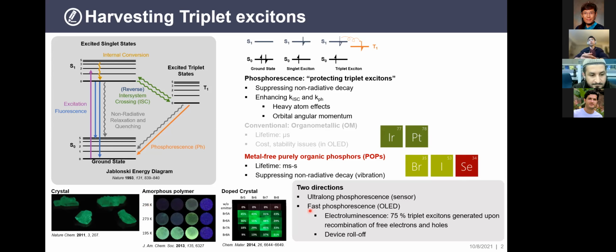Generally speaking, phosphorescence materials, or POPs, have two directions. One, intentionally you make the lifetime really, really long, and they are really good for sensors, and we call them ultra long phosphorescence. And another direction, we make them very fast, in terms of electronic devices, because in electronic devices you have a certain phenomenon called device roll-off, which means that when your triplet lifetime is really long, they ultimately will kill your device because they cannot be removed by emitting the light in a very fast fashion.